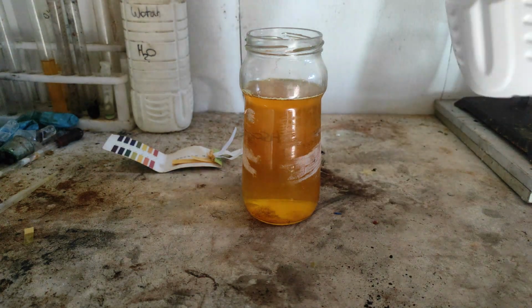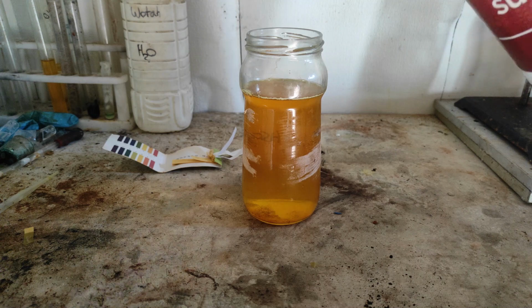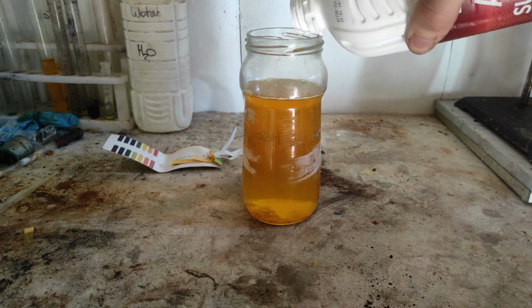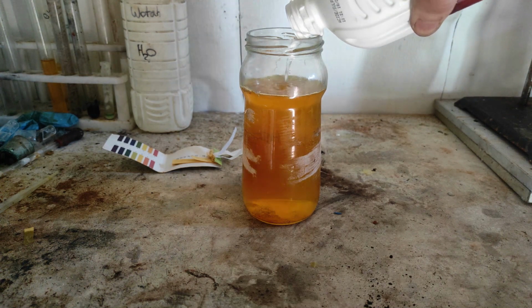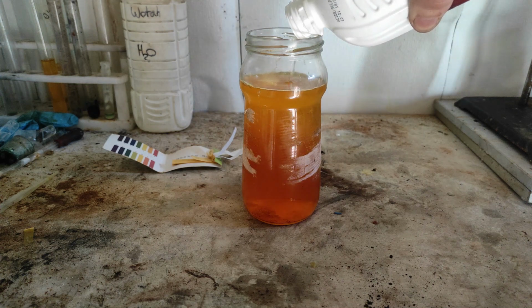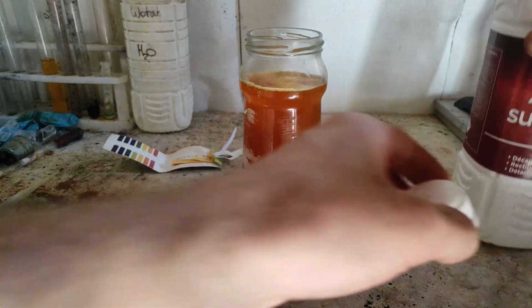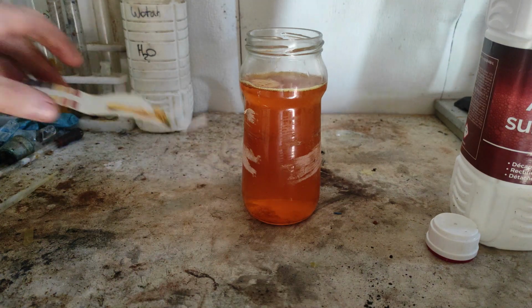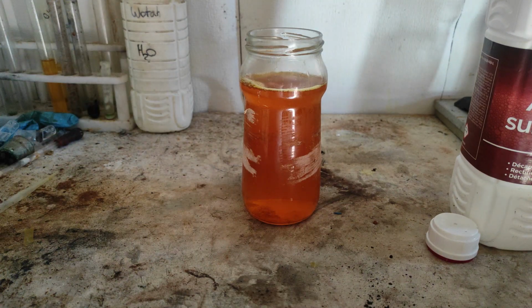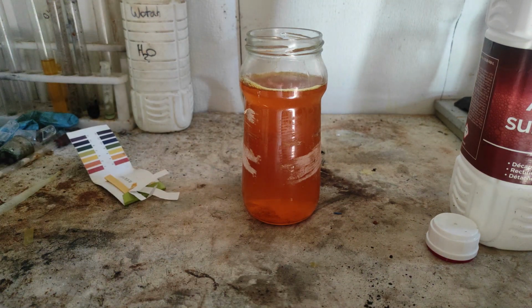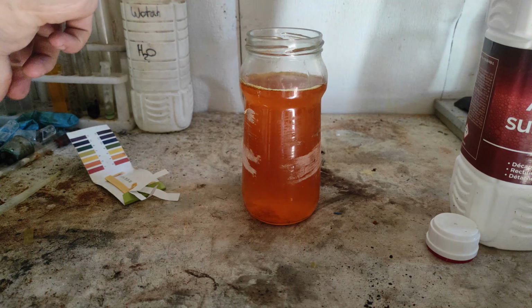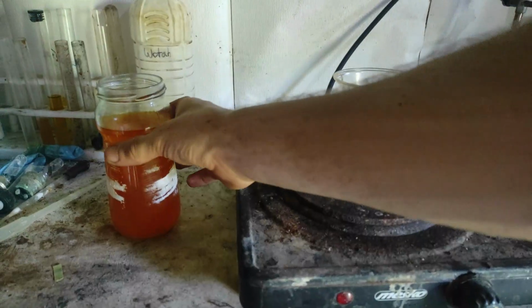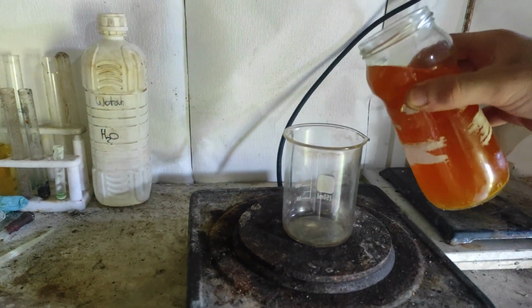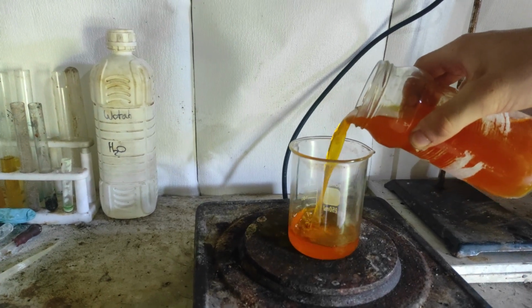We know the reaction is finished when the color gets a vibrant orange and the pH becomes acidic. If we add too much acid, we will start to form chromic acid. We can then boil down the solution until a precipitate gets formed. Then we cool down the product and filter it.